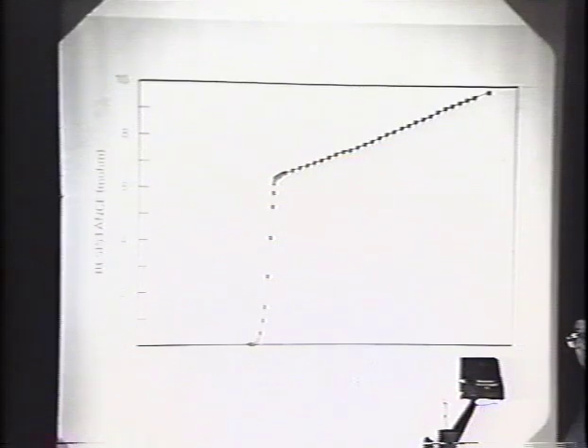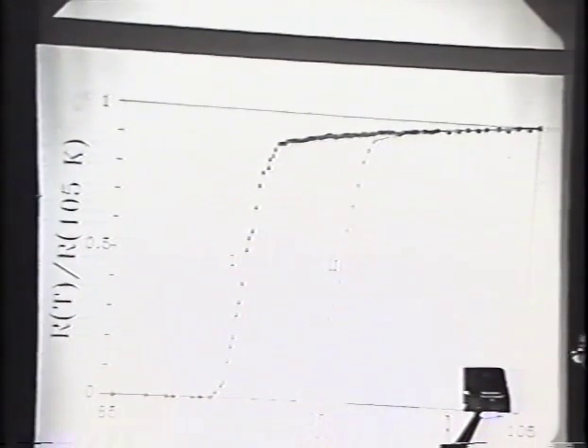Then on January the 28th, this was observed. And Professor Wu tried to impress people. In fact, he only measured it down to 77 degrees by using the liquid nitrogen dewar. As you can see, resistance really goes down. Immediately following that, we improved the temperature of the samples slightly, and a few days later we got the onset at 98 degrees, and it goes down to 0 at 94 degrees for the yttrium barium copper oxide.